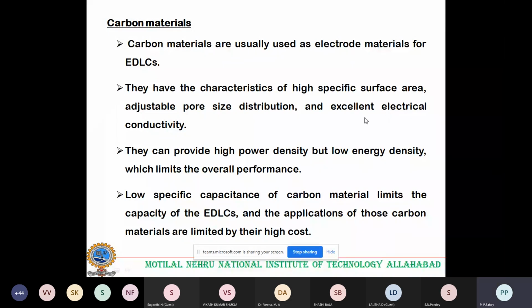They can provide high power density. That is, the specific power is high, but specific energy is low, which limits the overall performance. The low specific capacitance of carbon materials limits the capacity of the EDLC, and the application of those carbon materials is limited by their high cost. There is something which is good in the carbon materials, like the electrical conductivity, but there are certain constraints. That is, the supercapacitor based on carbon-based materials has high specific power but low energy, resulting in the overall performance not being up to that limit. Moreover, the high cost of the carbon is also a factor.